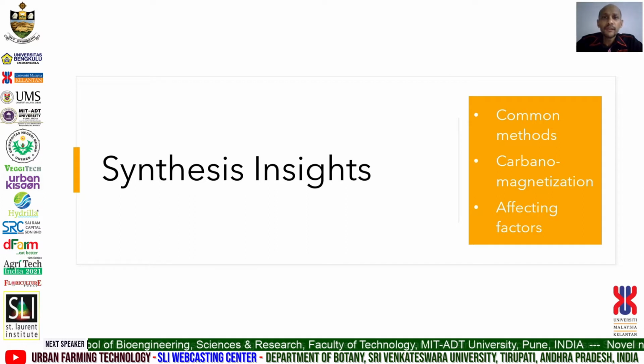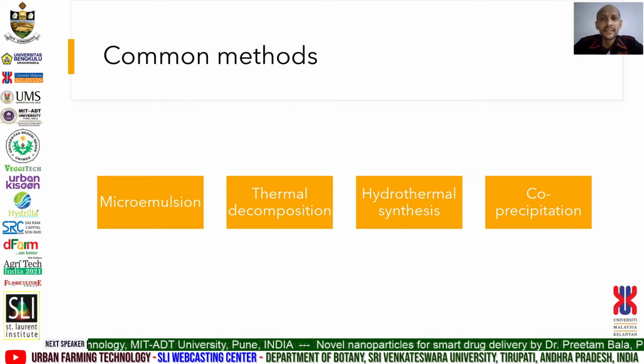Now, moving on to synthesis, there are actually many reported works on iron oxide magnetic nanoparticle preparation and synthesis. This includes microemulsion, thermal decomposition, hydrothermal synthesis, and co-precipitation, among others. As one convenient and cheap method, co-precipitation has the potential to meet the increasing demand for direct preparation of well-dispersed water-based iron oxide nanoparticles. This approach offers a low-temperature alternative in the production of nanoparticles and better size control.